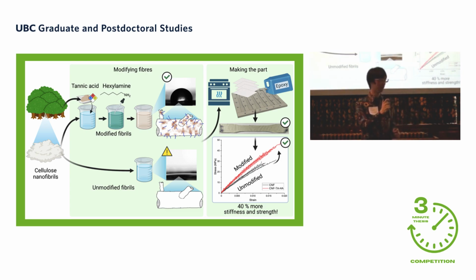Unfortunately, as with most natural materials, they do absorb water, they're hydrophilic. And we all know that oil and water do not mix. Composites are based on polymer resins, and these are oil-based. So even if you try to mix these cellulose nanofibrils into plastic resins, they simply won't work. The fibers will just pull out, and the resulting material is very weak.